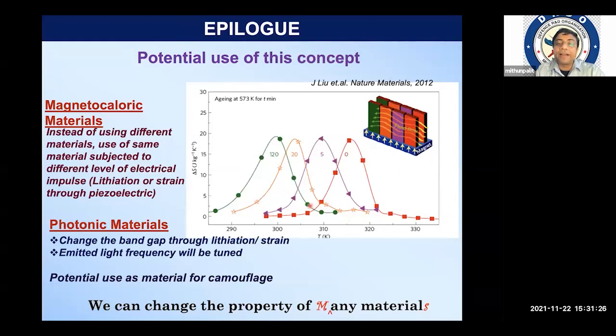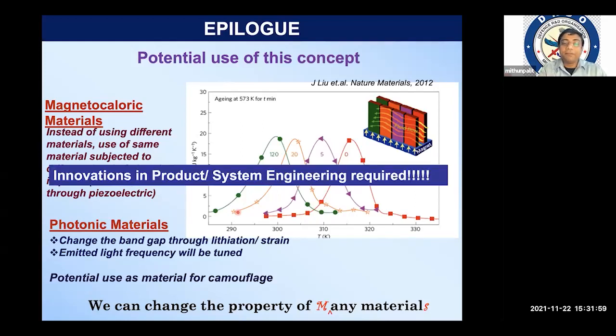The magnetocaloric materials I described are operable only in a particular range. However, if we can devise a smart magnetocaloric material which is amenable to electric field tuning or strain tuning, then by changing the electric stimulus or the applied strain, you can shift these transition temperatures, or shift the applicable temperature range, and get wide temperature range magnetic refrigeration. But it needs innovations in product and system. And my dream is that if not any material, at least many materials, we will be able to elevate into the class of smart material.